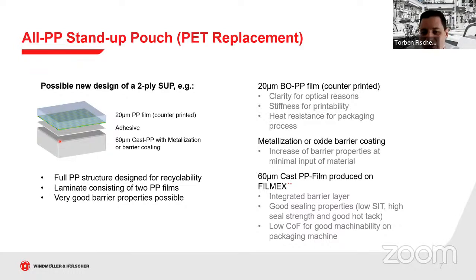And tests show that this new pouch system is able to be as good as your former pouch solutions, but has a quite advantage when it comes to recyclability. This product is made strictly from PP. You can refeed it to your processes. So by doing this clever design, you have a new solution which improves the recyclability drastically. Just let me show you a short picture.